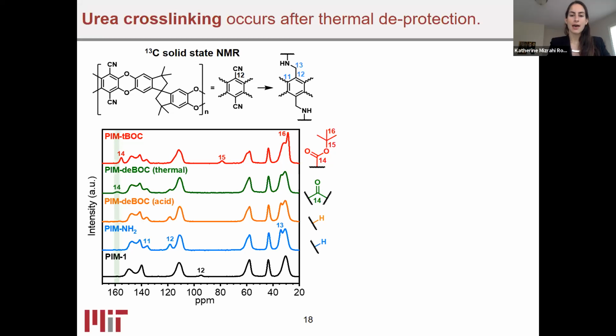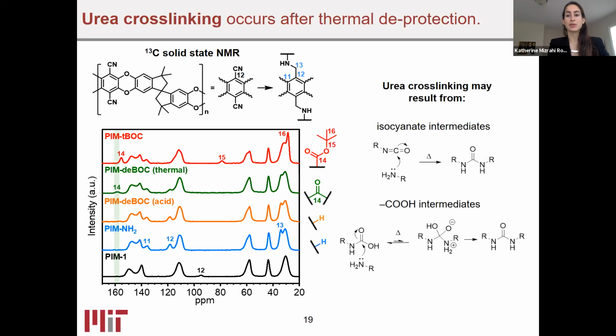So it should not be confused with residual TBOC functionality, but rather something else. After looking at both ChemDraw predictions as well as some of the literature on potential reaction mechanisms that can occur after deprotection, we found that this might be urea cross-linking, where isocyanate intermediates or carboxylic acid intermediates during the deprotection process can react with the already deprotected amine functionalized groups in the sample and result in urea formation, which can be small urea cross-linking throughout the sample upon thermal deprotection.